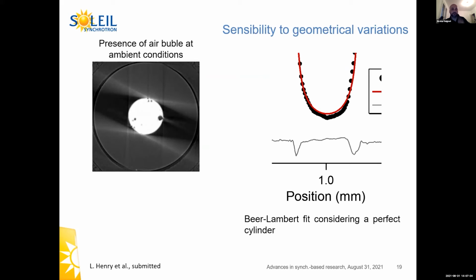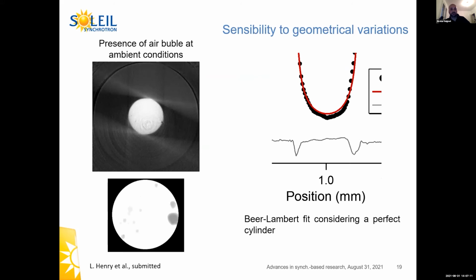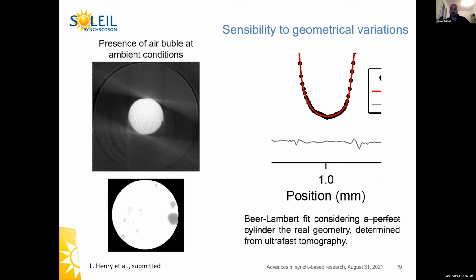Here, you see the strength of combining high-speed tomography with the absorption measurements, because now from this 3D reconstruction, it's possible to determine the exact geometry of the sample at the position of the absorption measurement, and produce another fit like so. So here, I'm considering not a perfect cylinder, but the real geometry measured thanks to high-speed tomography. And this is, to me, very interesting, because that means that we don't need anymore to consider a perfect cylinder. Maybe we don't even need anymore to have diamond capsules to make these kinds of measurements, since we know exactly the geometry of the sample at the position of the measurement.